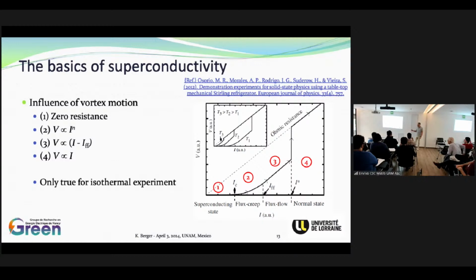Finally, we have a linear slope here in what we call the flux flow region. This one was the flux creep. And at the end, there is another, not critical, but another current that makes the superconductor a completely resistive material. So this kind of curve is true in an isothermal condition without thermal effects, but in fact, inside a material that is not pure, not homogeneous, you have a multitude of relationships like this, which make it smoother. But at the end, the relationship that we use is one where the voltage is related to the current to the power of a certain exponent. So this is what we call the power law.